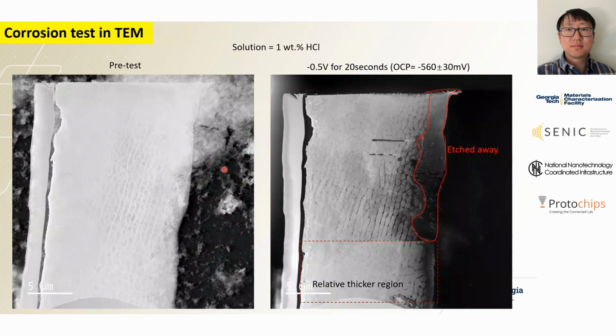We use this sample for the corrosion test, and the solution we use here is 1 weight% of hydrochloric acid. We previously used sodium chloride, but we didn't see any corrosion, so we had to use more corrosive hydrochloric acid. This is a piece of additive manufactured stainless steel before we put it into the solution, and we can see the network shows a bright contrast in this image. The open circuit voltage we use is minus 560 plus or minus 30 millivolts.